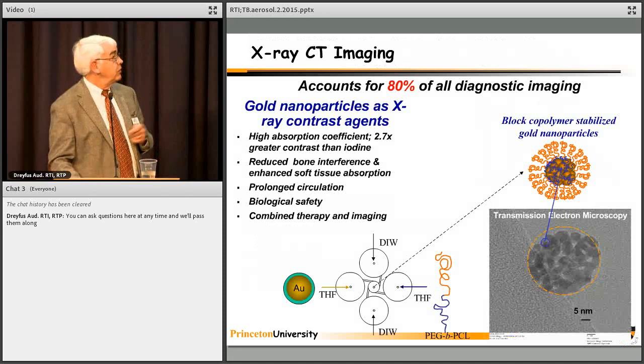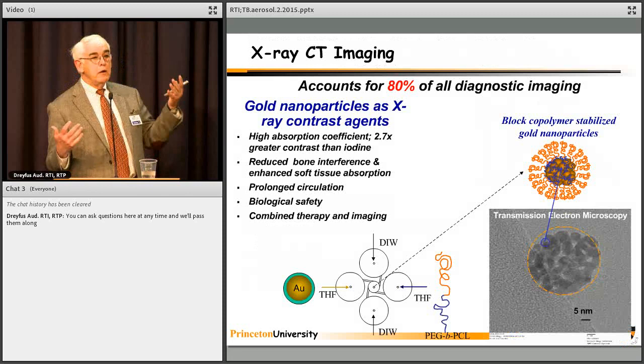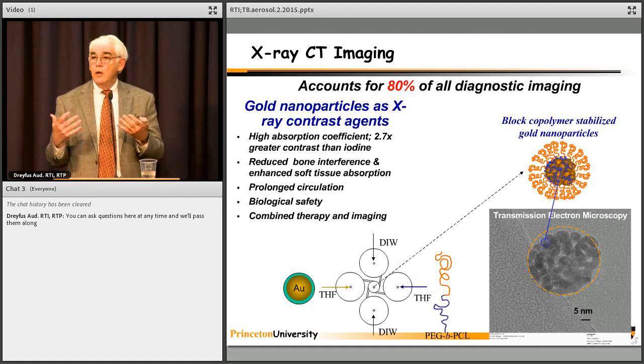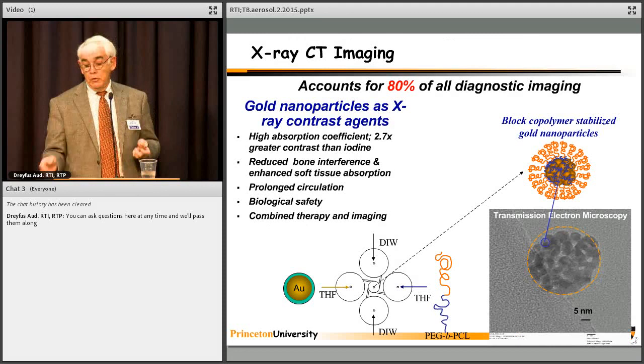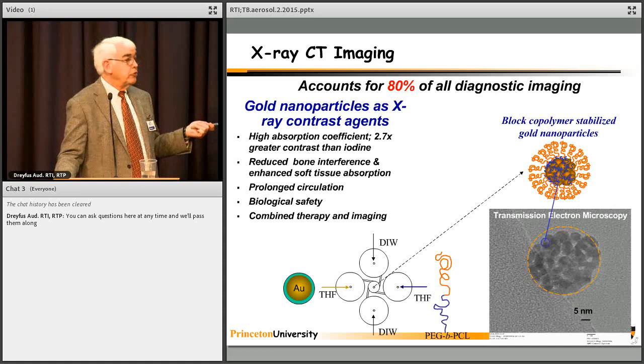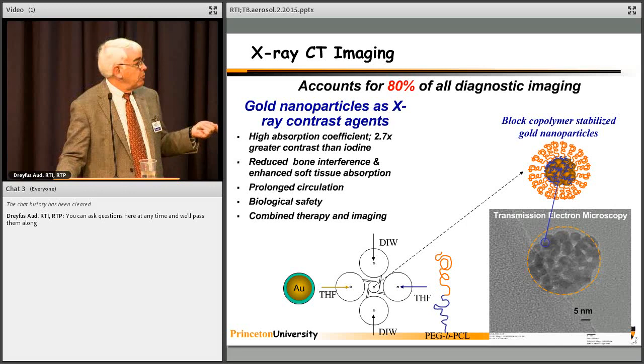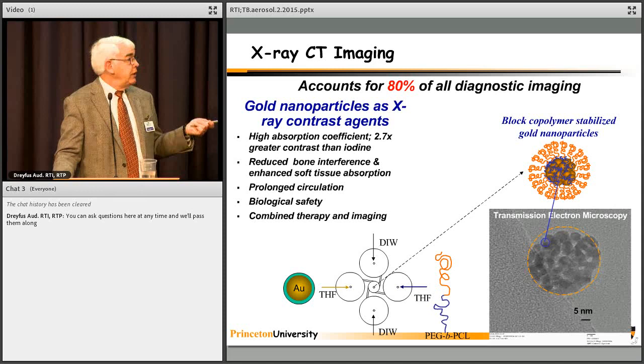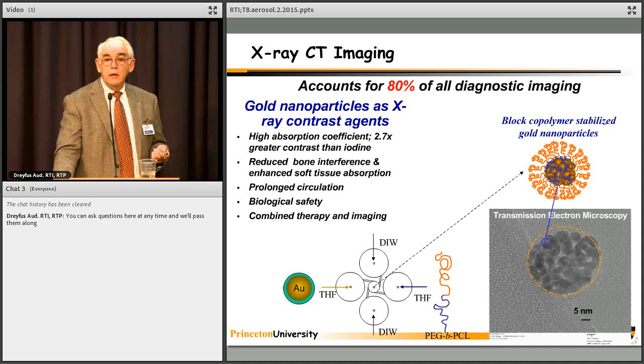In everything I've talked about so far, we've had a hydrophobic organic compound that we've precipitated. But there's nothing in our strategy that says it has to be an organic compound. It just has to be hydrophobic, so in water it will diffuse and stick. So Marion Gindy, my really talented grad student, said, let's try taking gold particles and putting a hydrophobic thiol, decane thiol, on the surface to make them hydrophobic, and put it through the precipitation process and see what happens. Well, you put it through this precipitation with a block copolymer, and you can make clusters of gold particles. This is in TEM, so you don't see the PEG surrounding corona, but these are PEG-protected, long-circulating and colloidally stable. So this would be of interest as an X-ray contrast agent, these gold particles.